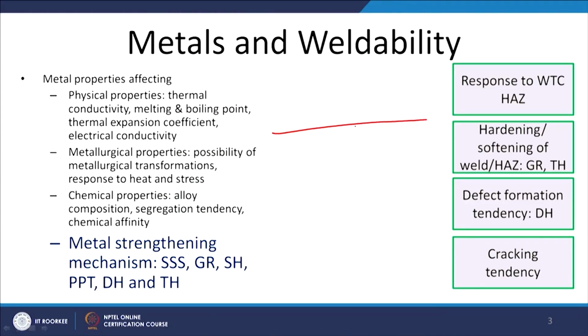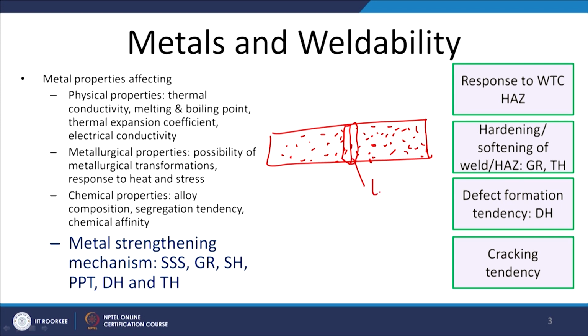In case of another solid state joining process, of the precipitation hardened materials where precipitates are there, where severe plastic deformation is achieved, all these precipitates will get fractured and they will get dissolved in the matrix. So again loss of precipitates will occur from the weld zone, and the heat generated is also more, so reversion or the loss of precipitates will also take place in the heat affected zone.